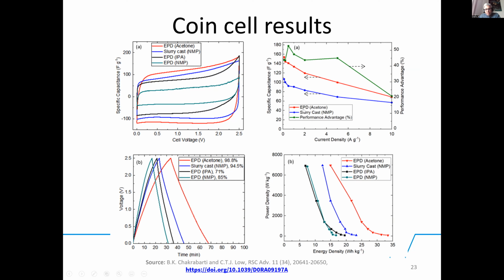where we compared EPD from the acetone solvent to slurry cast ones, and we found that at all the current densities that we tested, the acetone-based EPD electrodes were giving much better performances. Although the performance advantages decreased at higher current densities, they were still higher than 20% in comparison to the standard slurry cast electrodes. And then we did a Ragone plot as well, where we also showed quite high energy densities and power densities for the EPD electrode from the acetone bath in comparison to the slurry cast standard electrodes.